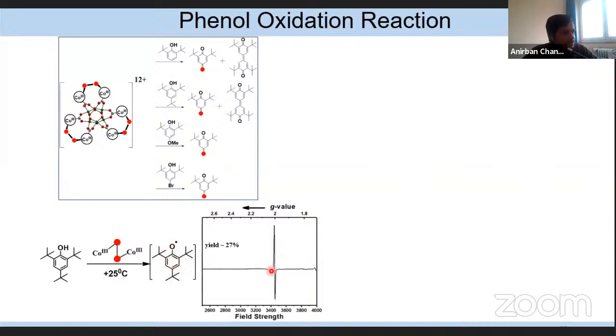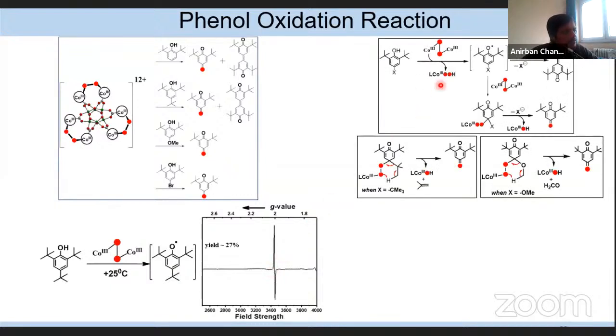So from this observation, I propose the mechanism where this phenol first reacts with the end-on cobalt peroxo species to form a phenoxyl radical, for which I get evidence from here, and this phenoxyl radical can dimerize in some cases to form this product, whereas this phenoxyl radical can again react with the end-on peroxo species to form the 1,4-benzoquinone product.